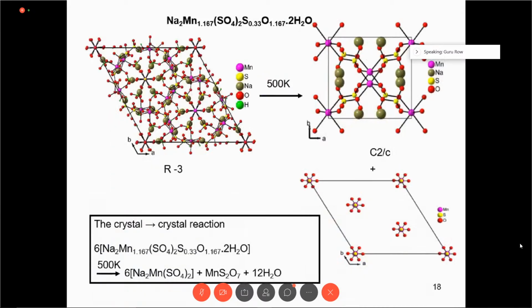So this is the high temperature X-ray data. And what is shown here is the reciprocal lattice image as we record the X-ray diffraction pattern. So the original pattern has this diffraction. And when we heat it to over 180 degrees, in fact, we went to 500 Kelvin. Notice that we are now talking in Kelvin. At 500 Kelvin, we get this remarkable phase separation. So it is possible, therefore, to identify these individual spots and then determine what that structure is. And this was the job which was done a decade ago. And what was found was that there is a remarkable phase transition.